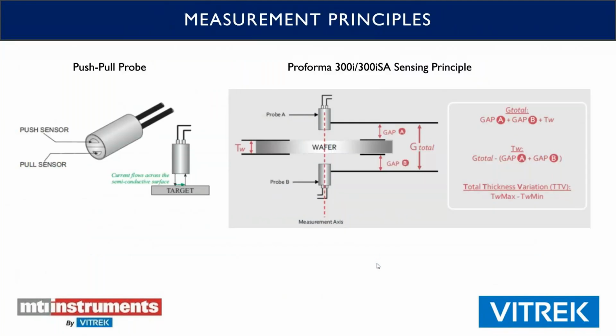So the measurement principles, with these tools, it uses opposing probes. Our push-pull probe is actually two sensors built into one probe body. As you can see on the left here, there's a signal that comes out of the push side of the probe, and it goes across the target to the pull sensor, which is run at the same frequency, but there's a 180-degree phase shift, which basically shoots the target down one side and then sucks it back up the